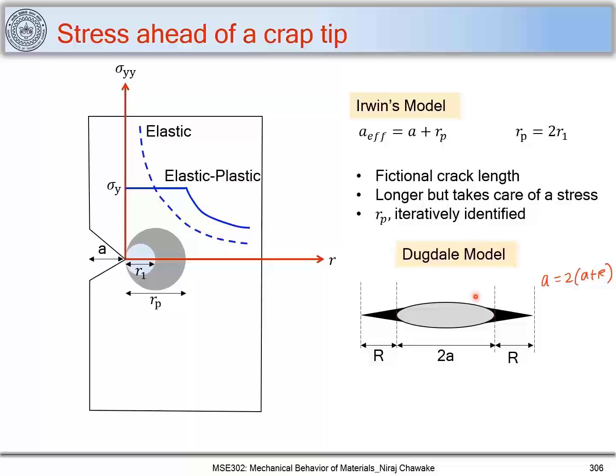And what Dugdale considered is that this plastic zone blunts the crack, and it can be considered as if there are compressive stresses acting on this region of R, which is nothing but the plastic zone. So we have an effective crack length of 2a plus R, and on this R part you have compressive stresses, and based on this assumption, this R can be found out to be equal to pi K squared upon 8 sigma ys squared, where sigma ys is the yield strength of the material. And you can find out the length of this plastic zone using Dugdale's model. I'm not going into the derivations of it. It's given in the Mechanical Metallurgy book by George E.